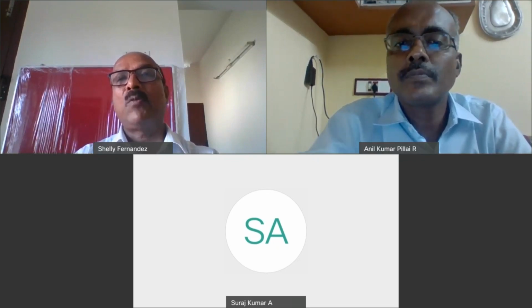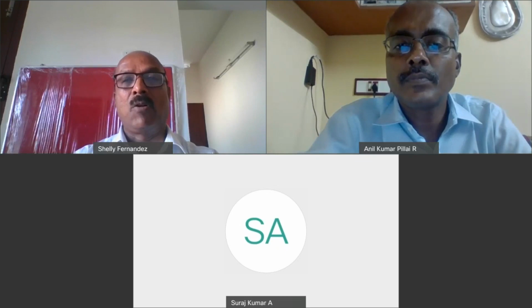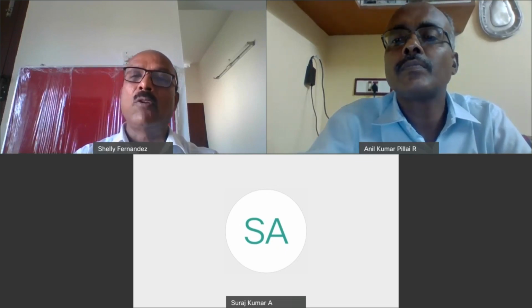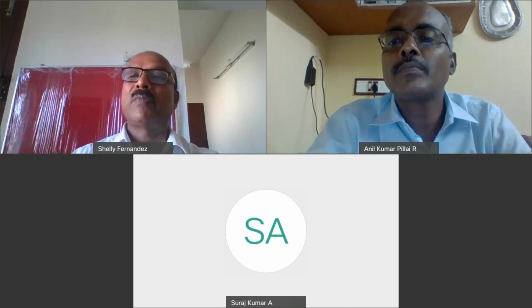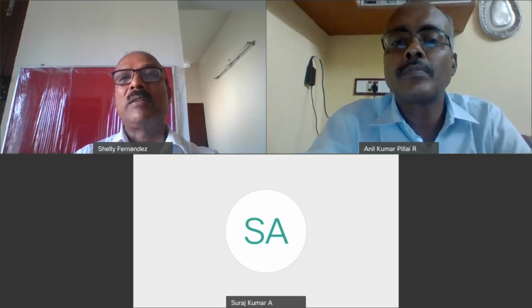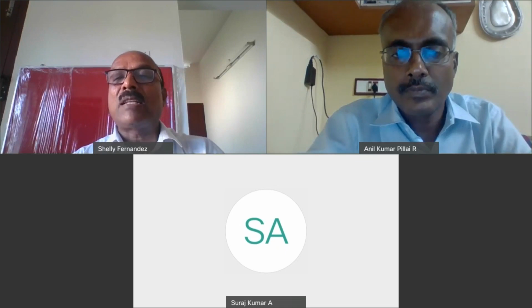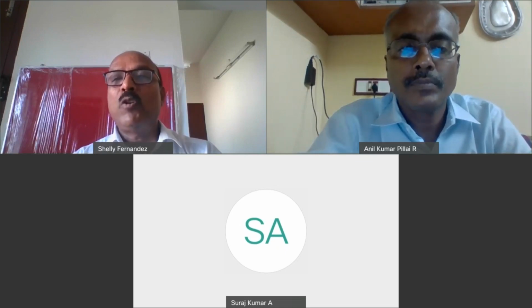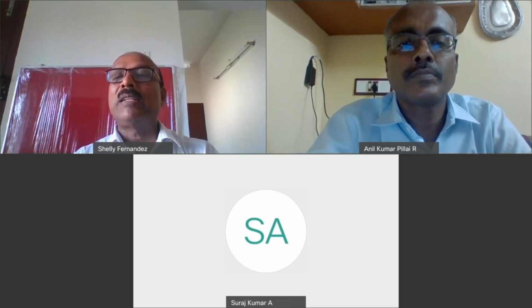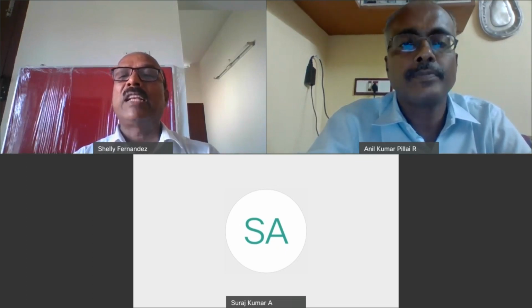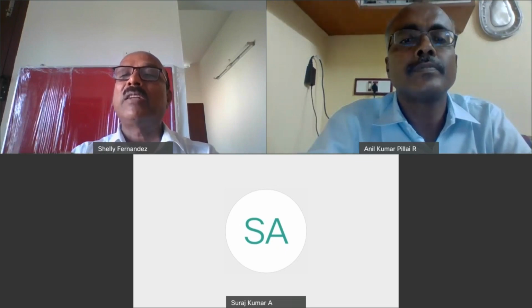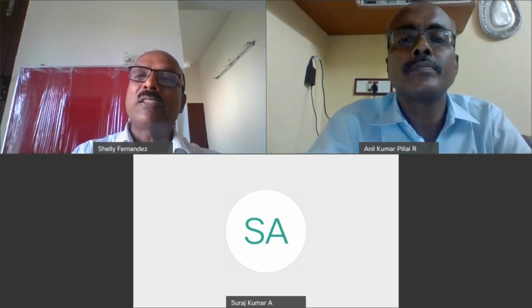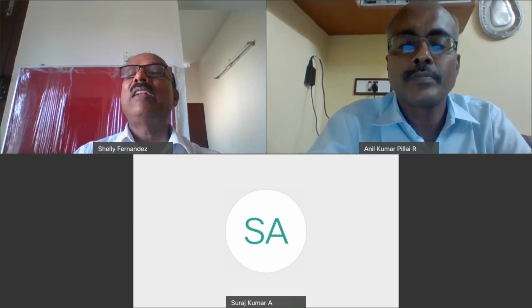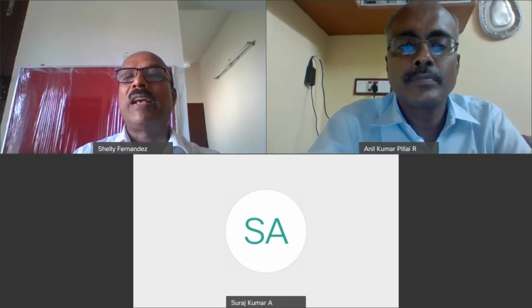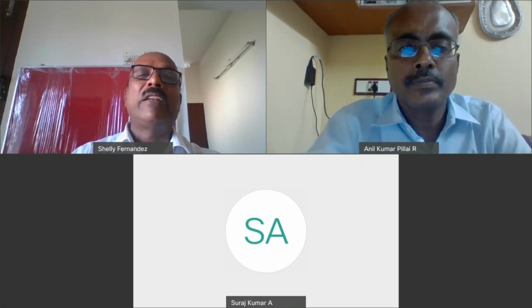Even in slabs, what happens? Suppose we finish concrete in the evening by 6 or 7 o'clock and people go home. In the evening also, hot wind is blowing over our slab. Due to this, the top portion dries up faster than the bottom portion. As when we burn a newspaper, you can see the curling effect. The same curling effect takes place in the slab, and this curling effect brings the shrinkage cracks. These shrinkage cracks are not structurally harmful, but they can go deep down. If not taken care of, they can cause leakage to the slab also.